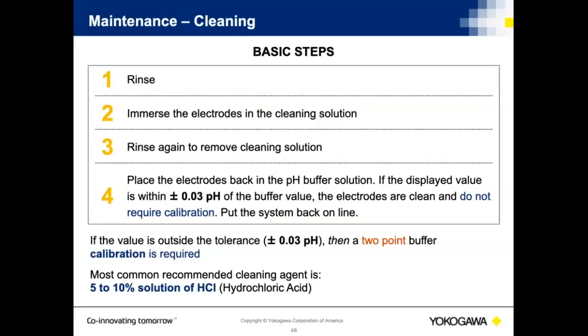I can tell you that in boiler applications, the pH probes typically do not get that dirty. If they get a buildup on them of iron or something else, there's probably something else going on in the boiler that people are going to notice much quicker than the pH actually changing. The point is, you want to establish some type of routine basis for cleaning and calibrating the probes or checking the calibration. And a lot of our different manuals go into some of the detail on how you should establish that.